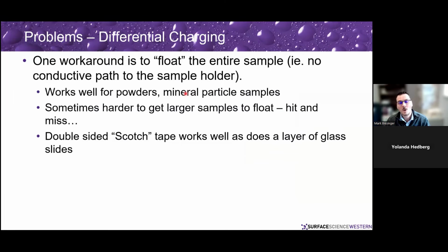One of the ways to work around this is to electrically isolate or float the entire sample, so there's no conductive path to the holder. And you can do this by putting it on a glass slide or on double-sided non-conductive adhesive. Generally works well for powders, mineral samples. We do all sorts of materials now, even things that are metallic, have underlying metallic samples. We generally do a lot of our work now with the samples electrically isolated and use the charge neutralizer to get things to work.